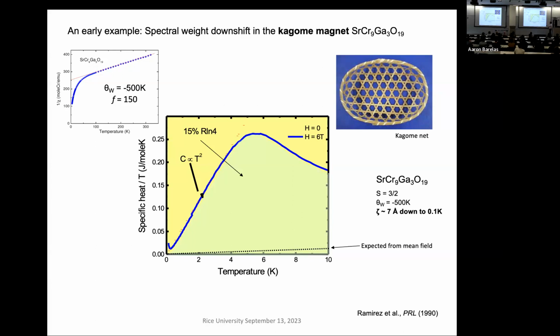Nevertheless, it still looks like it has good free ion behavior. The slope gives you the moment of the chromium ion, and it agrees with the theoretical value for chromium. And this downturn is where correlations are happening and it gets lost. But one of the important things is that if you go down to this low temperature region and look at the specific heat, here's an example. You get about 15% of the total entropy at an energy scale that's 2 orders of magnitude lower than the Weiss constant. This is kind of the nature of frustration. This is a common characteristic.